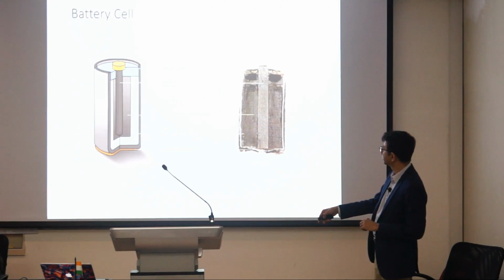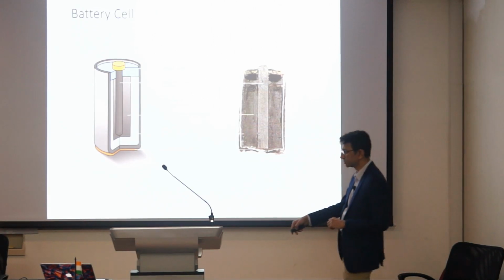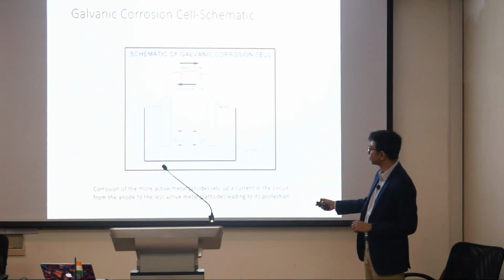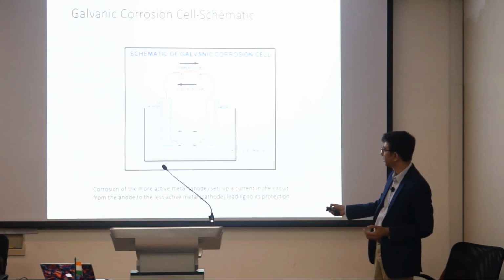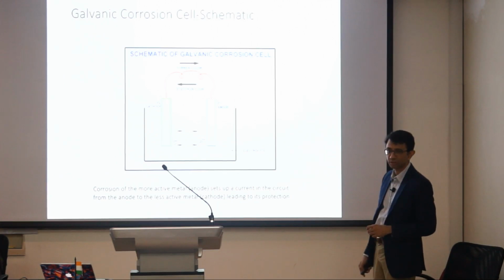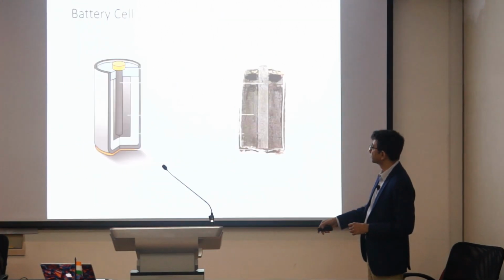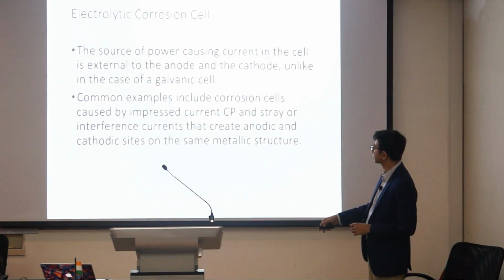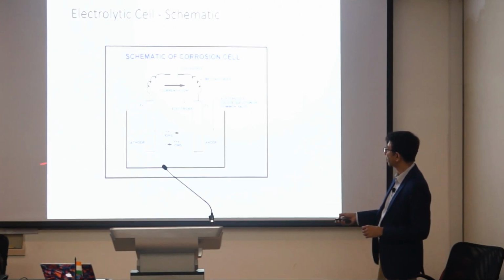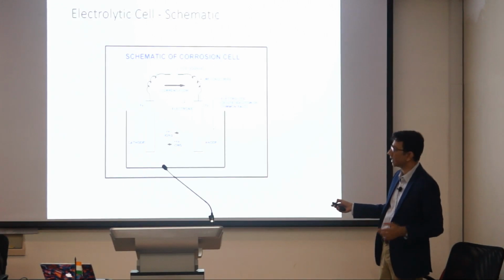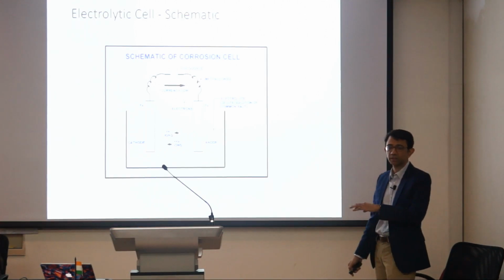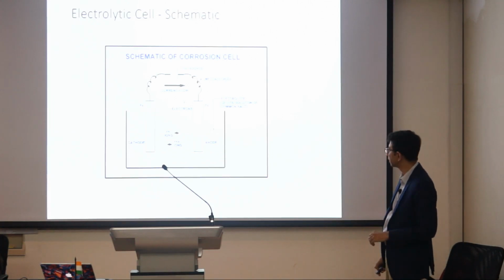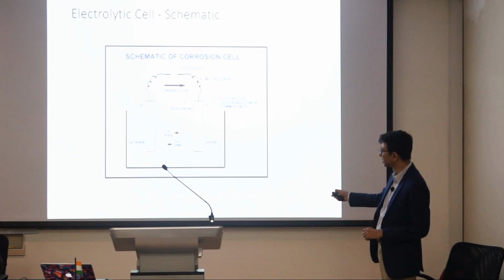In the first case, which we saw some time back, the galvanic cell, you can see that there is no external source of power. How does this power happen? The power is the result of the natural difference in potential between these two dissimilar metals. But in the case of an electrolytic cell, look at this slide. So you have a DC source like a battery, maybe a 9-volt battery, and you have two sheets of iron, the same metal, and you connect the positive of the DC battery to one, the negative to the other. And now what you've done really is you're polarizing one sheet positively, you're polarizing the other sheet negatively. You're forcing current out through this iron sheet, and because you force it out, this is going to corrode.